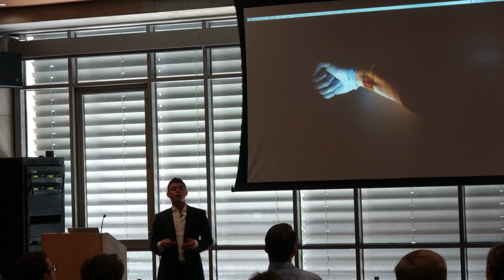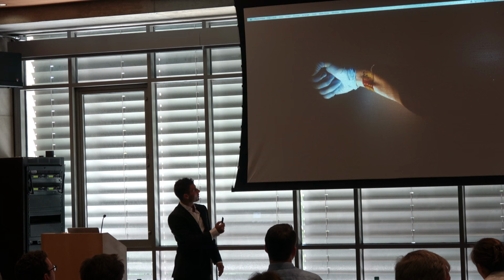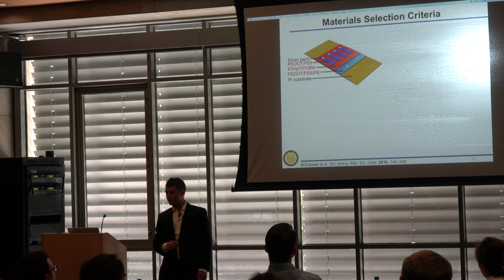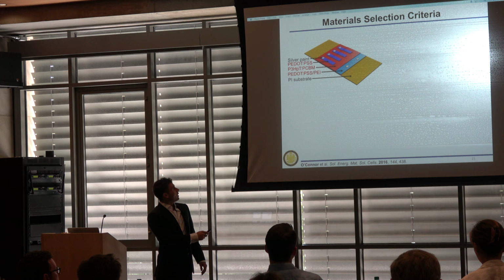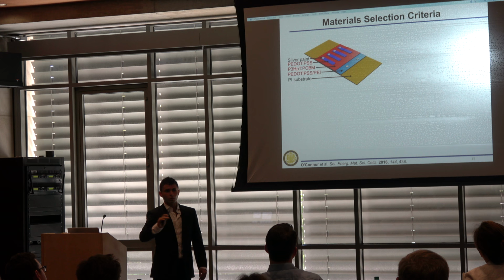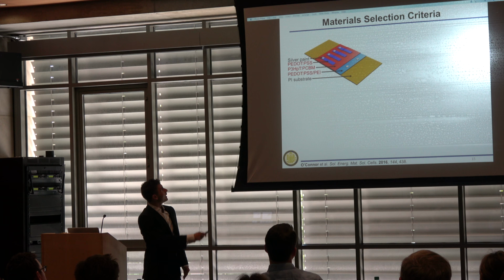So this is an image of the wearable solar cell. Here's a schematic. It was built on a 14 micron thick polyimide substrate. So these were ultra-thin devices that layer by layer we have PEDOT:PSS, and we used polyethylene imine to lower the work function of the PEDOT:PSS, and this allowed us to use PEDOT:PSS as both the top and bottom electrode. And now we used P3HT, so PCBM, as the active layer.